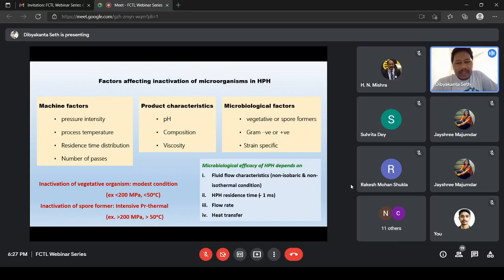Viscosity has no direct relation with the microbial inactivation, but viscosity will decide the residence time of that liquid in the valve gap, and that will decide the final lethality of the process. Whether it is vegetative or spore formers, as you know, the spore formers are more heat resistant. Gram negatives are more prone to heat and pressure effects. Even some of the effects are strain specific.